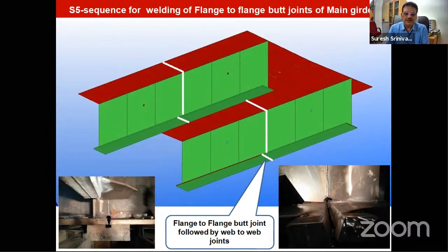So we had to change the web plate design by introducing two more stiffeners on either side of the butt joint. This was suggested by me, accepted by the designers as well. Because there is going to be a heavy stress in this plate, especially the 63 mm, 75 mm flange to flange plate, even though you do preheating, post-heating, whatever you want, the stresses could not be brought down as low as we would like to have.